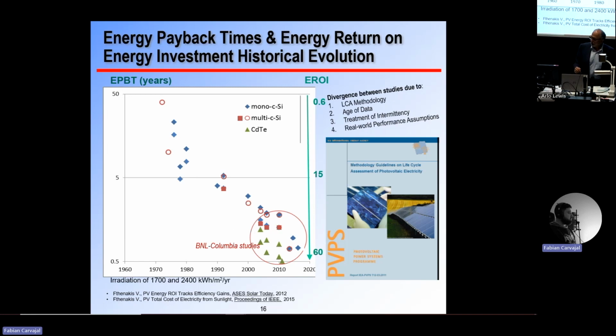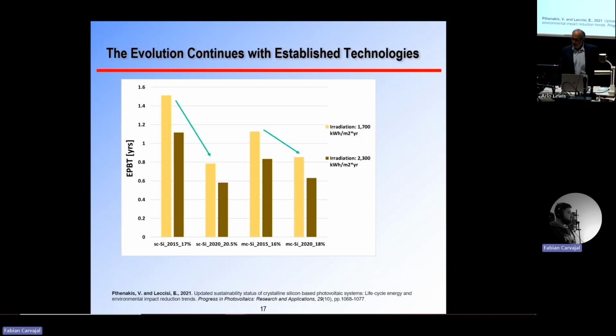So that's why, as Ken mentioned, we founded, under the IEA auspices, the International Energy Agency Task 12, and with analysts in 14 countries, we developed guidelines and assumptions that make, I think, the whole literature results more credible. Now, the evolution continues with established technologies. In silicon, for example, taking 5 years between 2015 and 2020, we have a betterment of about 45% for the energy payback times in crystalline silicon because of efficiency increases from 17% to 20.5%, but also, most importantly, because of much better material utilization. We have diamond cutting, we have thinner cells and a lot less kerf loss, down to 65 micron from 145 that we had before with the multi-wire slurry type of saw.